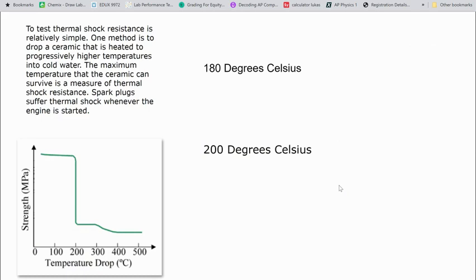So to test thermal shock resistance, you simply take a ceramic and heat it to progressively higher temperatures and then drop it into cold water. And we're looking at the maximum temperature that the ceramic can survive before it starts to become brittle and eventually break, right? So spark plugs in your car can suffer thermal shock when the engine is started.